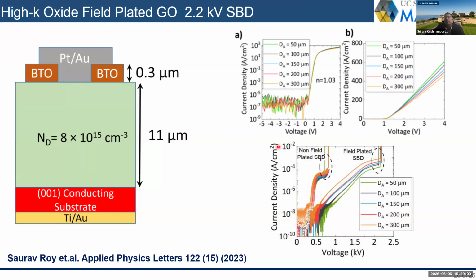and with low doping. And you can look at these log IV curves. These are very ideal diodes, Schottky diodes, essentially ideality close to 1, nicely scaling with area. And the breakdown voltage was also constant across 50 micron diameters to 300 micron diameters in this particular device. And we were now able to get up to like 2.2 kV Schottky diodes on gallium oxide layers with a high K field plate.